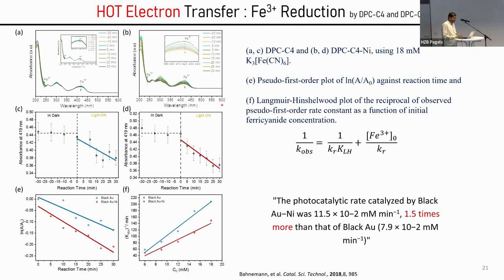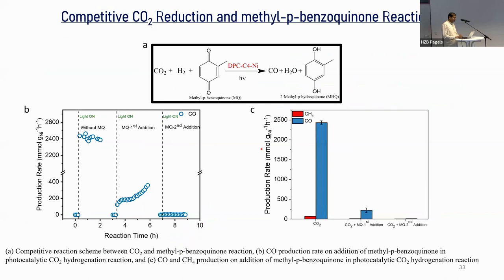And we saw that the black gold nickel has a better ability to transfer the electron and convert Fe3+ to Fe2+ as compared to only black gold. Again, true. Another one, we carried out the same reaction, CO2 hydrogenation, but now in the presence of an electron quencher, methyl-p-benzoquinone. So what will happen now? Your black gold nickel has this quencher. So now the electron will either go to the quencher or to the CO2 or hydrogen. And there is a competition. And you can see now, the quencher is an organic molecule nicely localized onto the surface, whereas CO2 is a gas.